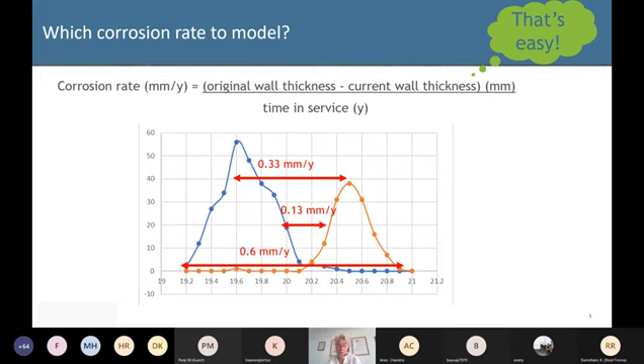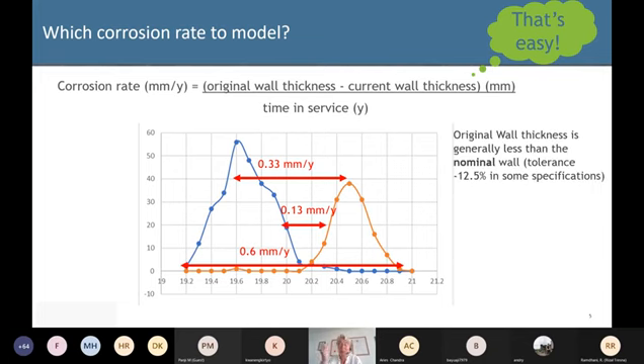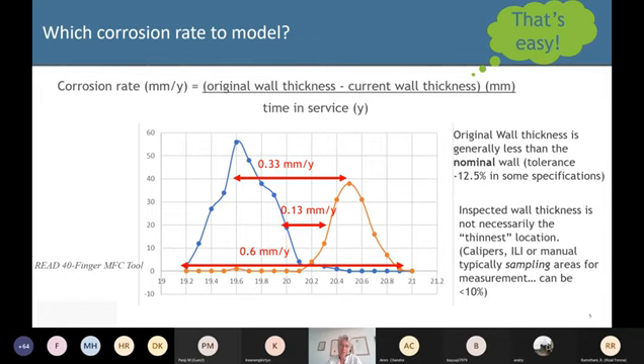for the current wall thickness. We normally work from the nominal. If you think about risk-based inspection or something, you say, well, what was it originally? It's the nominal wall thickness. But the tolerance is up to minus 12.5% of the wall thickness in some specifications, and things like fittings can be very variable in wall thickness. So it can be actually quite a lot thicker on one side and thinner on the other side. So that's something to keep in your mind.